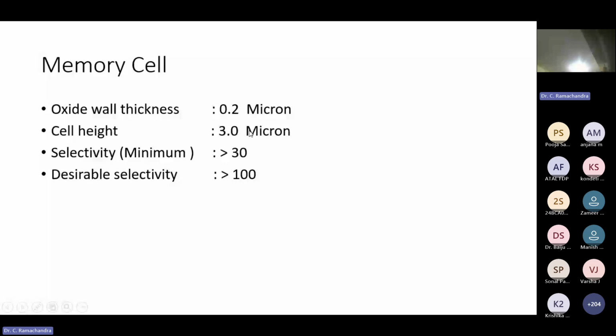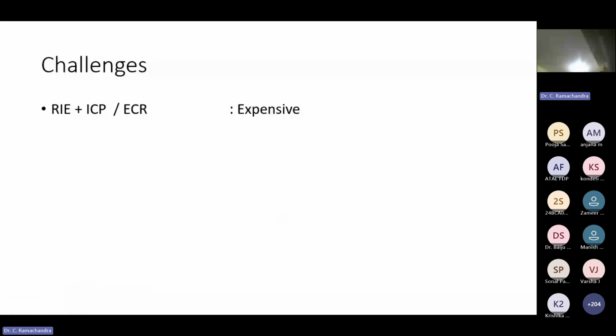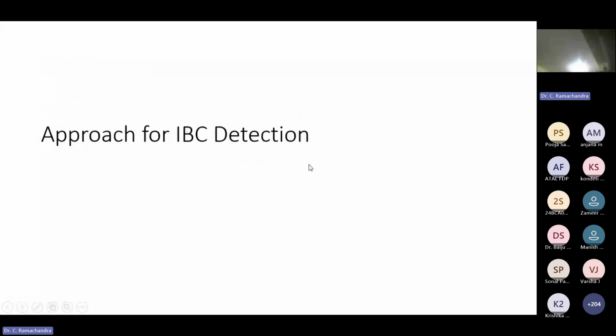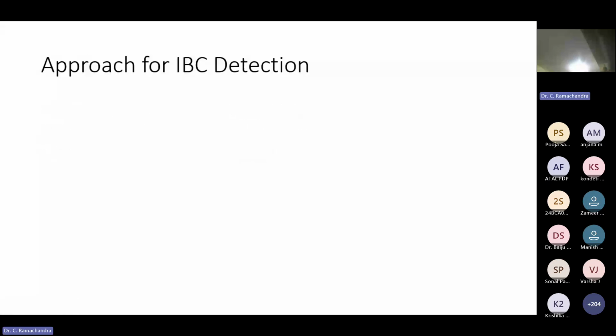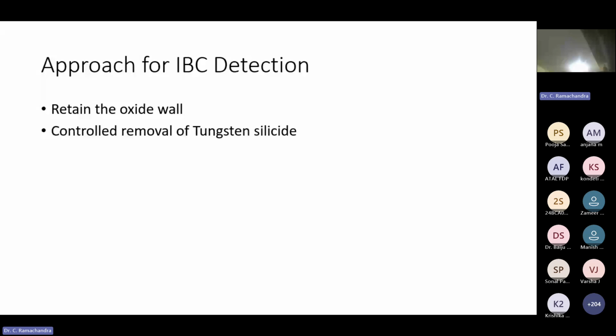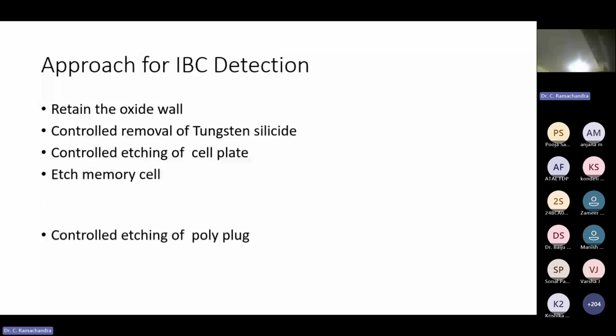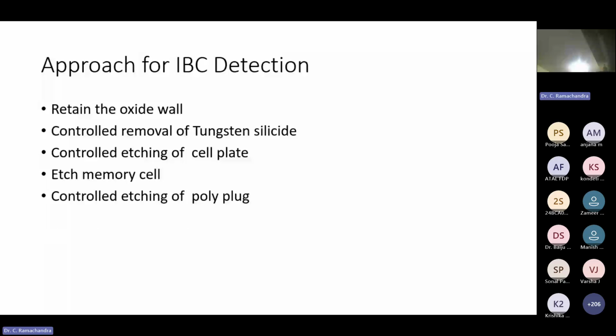So these were all various challenges we had actually. And we did not have a very expensive system like ICP or ECR, because their maintenance cost is very high. We did not have certain high selectivity chemicals because they were not used, because of their hazardous nature. Whatever method I tried had to retain the oxide wall. That is very important. Even though it is 0.2 micron oxide thickness, I should make sure that it does not get damaged, and controlled removal of tungsten silicide and controlled etching of the memory cell, the cell plate, is required. Then each memory cell I have to remove, and I have to etch the polyplug. Then I can see whether it had made a good contact or not.